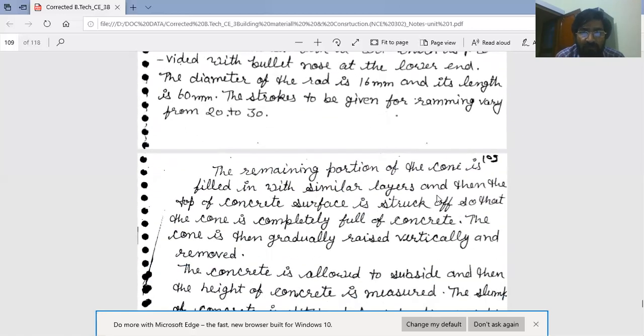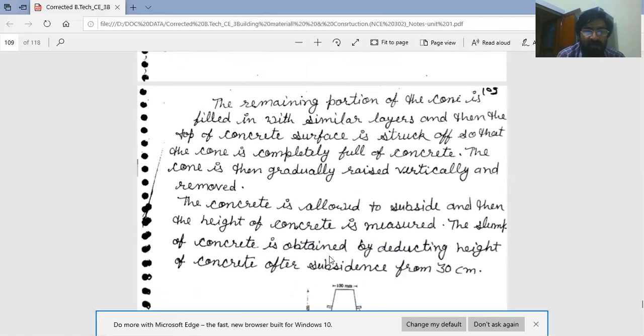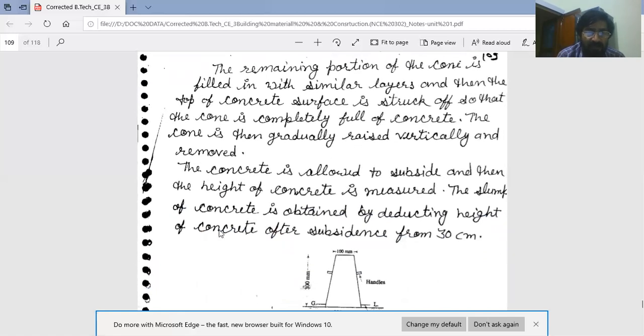The strokes given for ramming vary from 20 to 30. The remaining portion of the cone is filled with similar layers and then the top of the concrete surface is struck off, so that the cone is completely full of concrete. The cone is then very carefully raised vertically and removed. Now the concrete is in a wet state, and it is allowed to subside, and then the height of the concrete is measured. The slump of concrete is obtained by deducting the height of concrete after subsidence from 30 centimeter, because the height of the cone is 30 centimeter or 300 mm.